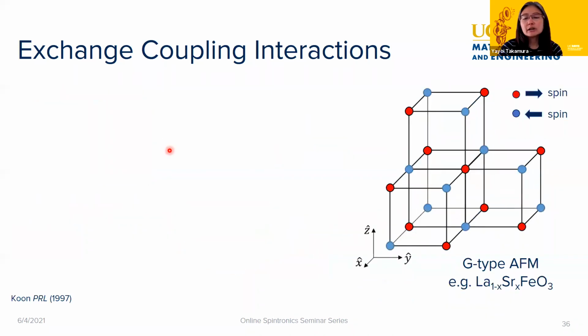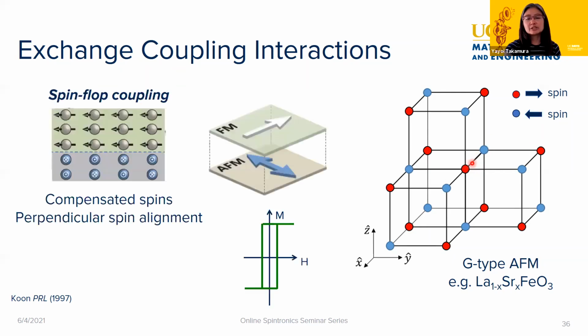But then the question is, what happens if you have a G-type antiferromagnetic material? Our LSFO is a G-type antiferromagnetic material, where if you look at one iron atom, say this red one, all its nearest neighbors are anti-parallel to it. I removed the lanthanum, strontium, and oxygen ions; these are just your magnetic iron atoms. So if we look at our 1,0,0 surface, you have an equal number of blue and red spheres, which means we basically have an equal number of opposite exchange interactions.